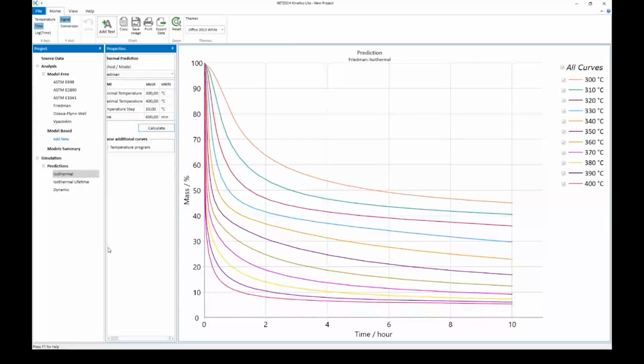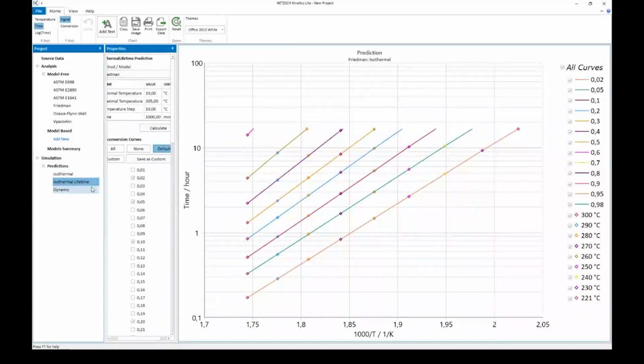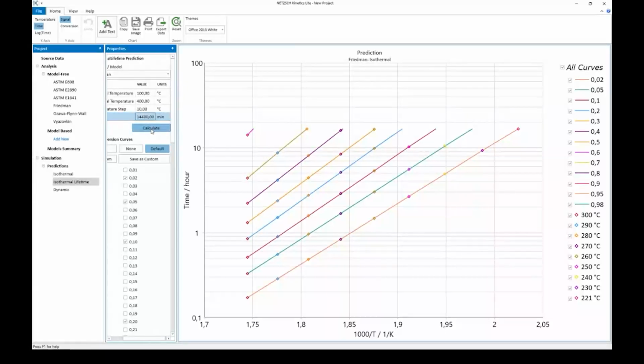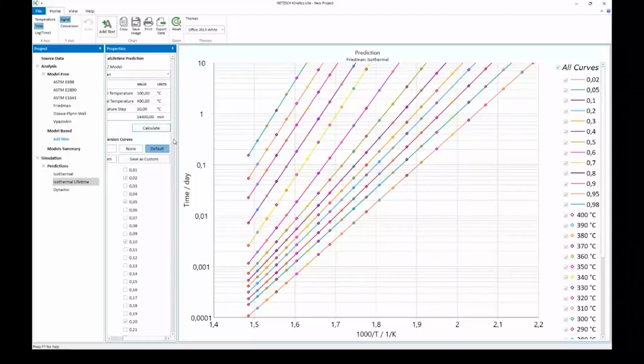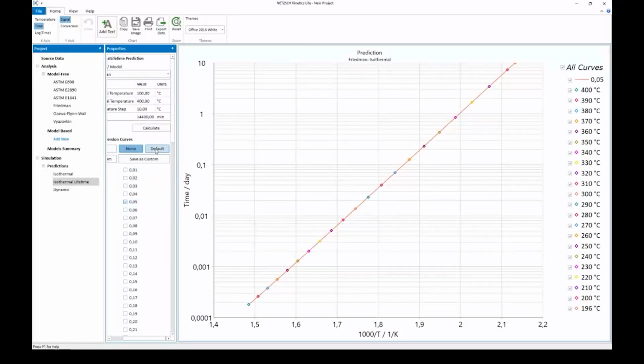And now our last question: at what temperature does the material have 5% of conversion after 10 days? Let's go to isothermal lifetime. We will search between 100 and 400 degrees C. We don't know at which temperature. We have some range, and we will try to search, and then it will be 10 days. 1 day is 1440 minutes, and 10 days is 10 times that. Calculate, and now we must find 5%, only 5%, this one.